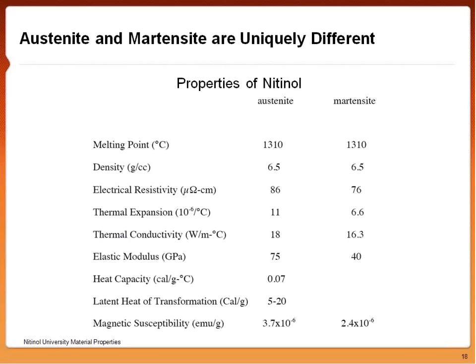When we look at the different sets of properties that austenite versus martensite have, we can see that there's no difference in density. However, there's a difference in electrical resistivity, thermal expansion, thermal conductivity, and even magnetic susceptibility. The key thing between the two phases is that there's no change in density. This is important for exhibiting the superelastic and shape memory effect. The fact that there is no change in density highlights some of the inner workings of the twinning process, which I'll describe next.